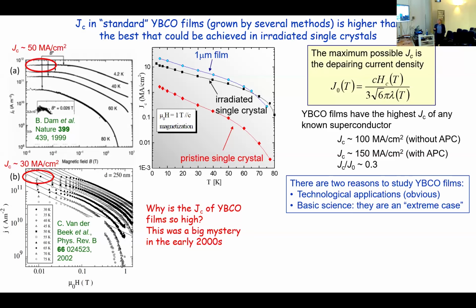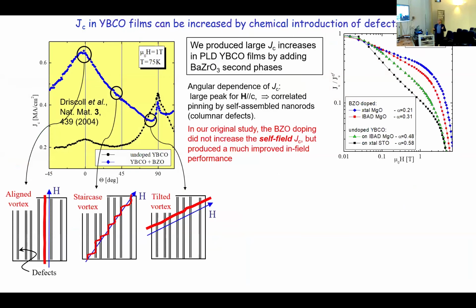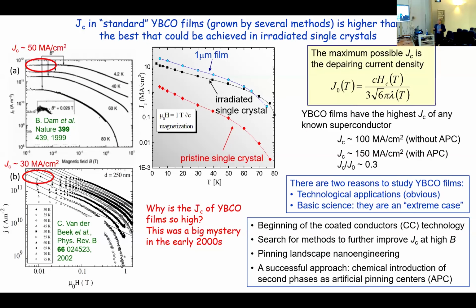In fact, if we look at the maximum possible current that you can produce in a superconductor, that is the depairing current, it turns out that YBCO films had the highest JC of any known superconductor, in terms of absolute values, exceeding 100 or even 150 megaamps per square centimeter, and in terms of fraction of the depairing current. So my point always is that it's always interesting to study YBCO films and coated conductors not only for the obvious technological interest, but also for the basic science interest.